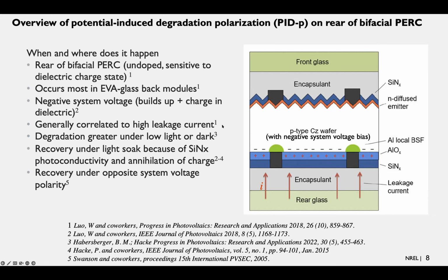And yeah, so that's what's going on there. It occurs most in EVA glass-back modules. The encapsulant would be EVA, and that's because historically, typically, not always, but generally speaking, the conductivity of ethylene vinyl acetate is higher, leading to charge transfer and leakage current through the rear. It occurs in negative system voltage.